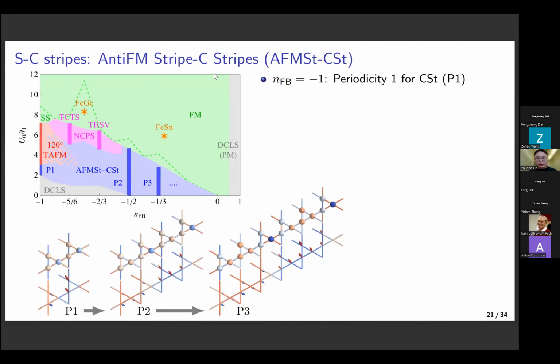So for example, if we first look at the empty flatband, that is the regime here, and if we look at the charge pattern of the ground state, we'll see that although there are some higher and lower charge density stripes, the translation symmetry between different unit cells is not broken, so we have a periodicity 1 for the charge stripe. However, if we look at the spin sector, we will see that the higher density stripes are actually having antiferromagnetic order between different unit cells. So the magnetic order is actually breaking the translation symmetry and enlarging it to 2.